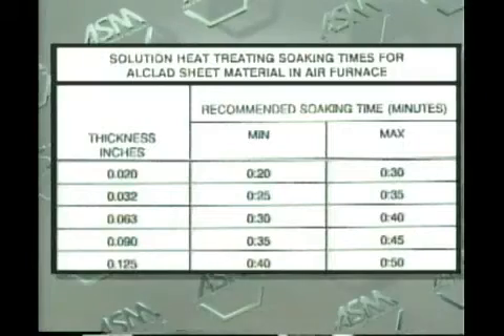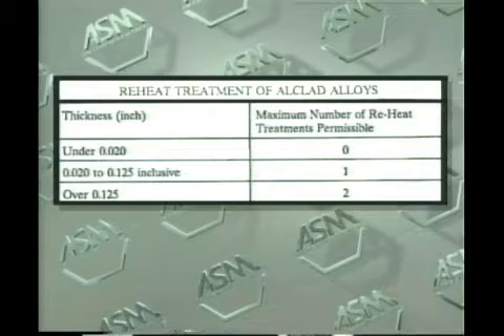Suggested maximum solution heat treat soaking times for sheet alloys are shown in this table. Alclad products of the 2000 and 7000 series alloys are normally not re-solution heat treated more than the number of times specified in the next table. One additional reheat treatment is permitted beyond the limits of the table if the heating rate is sufficiently rapid, such as salt bath heating, so that the material will satisfactorily pass an intergranular corrosion test.